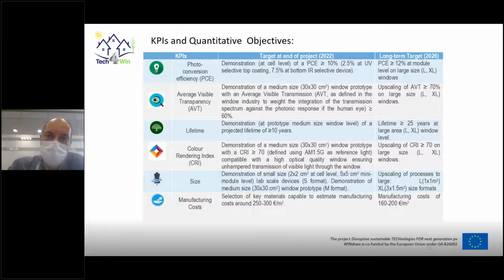We want to demonstrate in this term a medium-sized window prototype with a size of 30 × 30 square centimeters with an average visible transmission higher than 60%. This is the figure we are using. The average visible transmission is defined as the integration of the transmission spectrum weighted by the photonic response of the human eye. In terms of lifetime, we want to demonstrate at prototype medium-sized window level a lifetime of higher than 10 years at the end of the project phase, even if this will have to be extended up to 25 years in the long-term target.